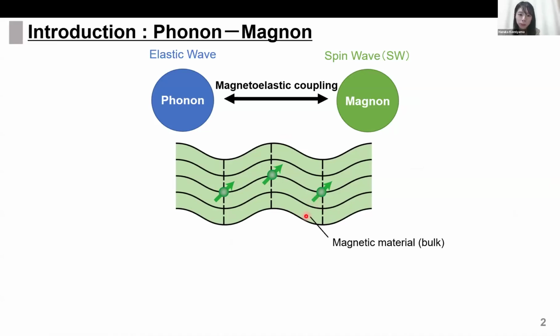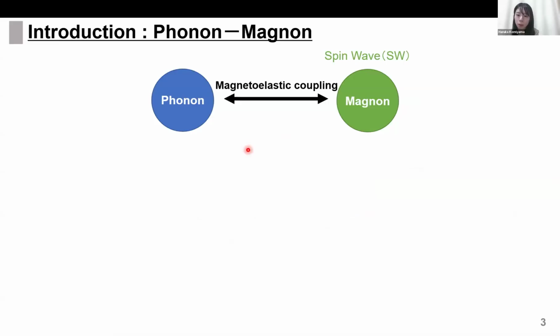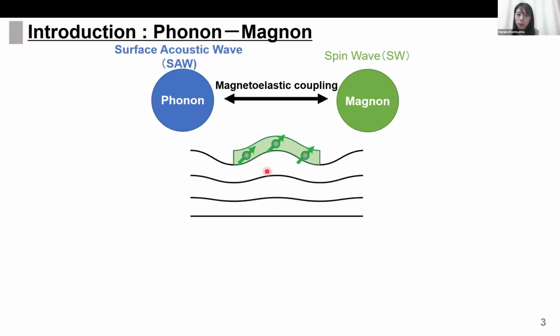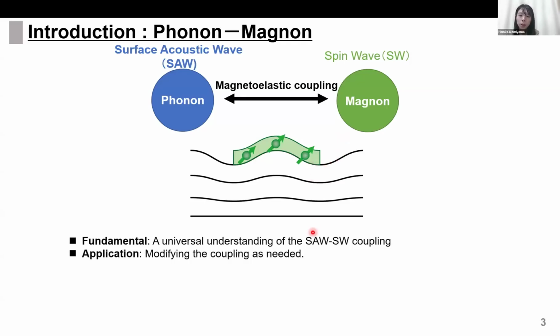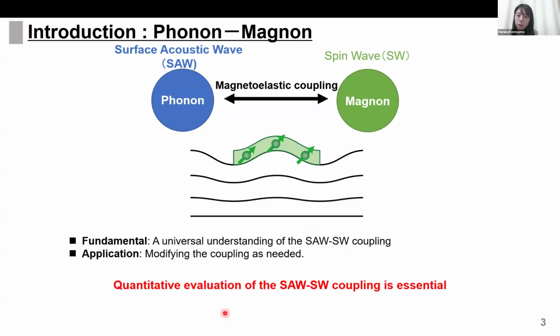its reverse effect. We focus on a coupled system localized on the material surfaces, in other words, surface acoustic waves and spin waves in magnetic thin films. They also interact by magnetoelastic coupling, but the interaction in thin films is smaller than in bulk. As a result, there are still few studies evaluating the coupling, and a universal understanding of coupling is insufficient. In terms of application, it is necessary to adjust the magnitude of the coupling as needed. In both the fundamental and application aspects, quantitative evaluation of coupling is essential.